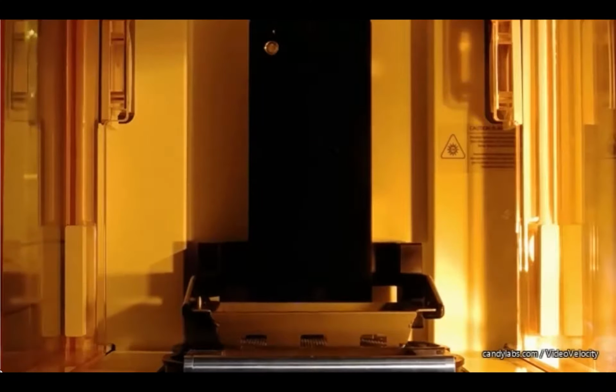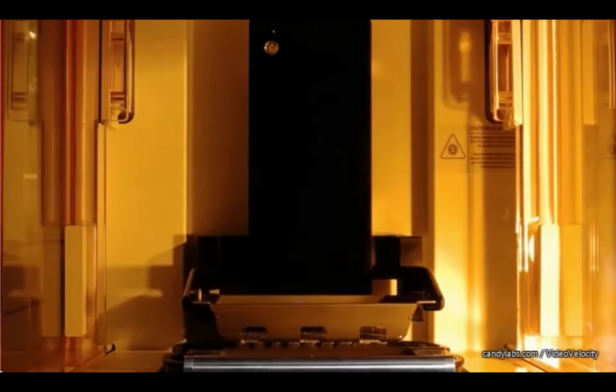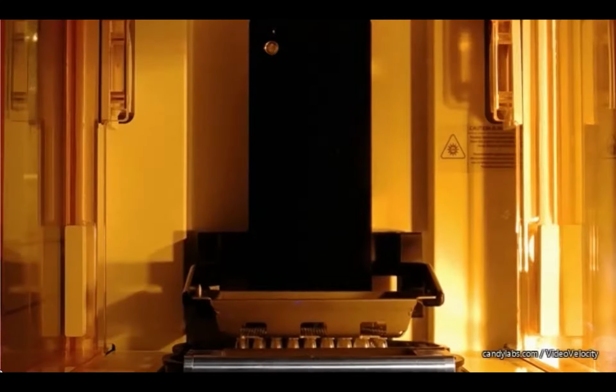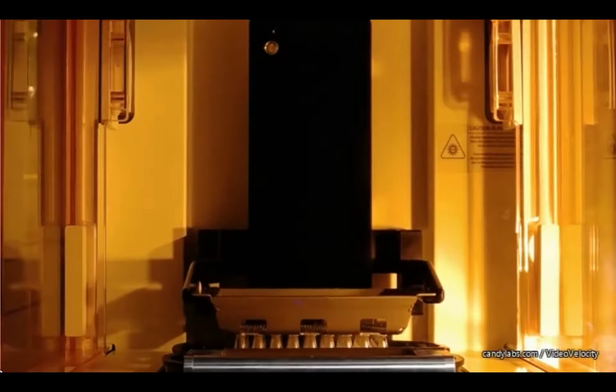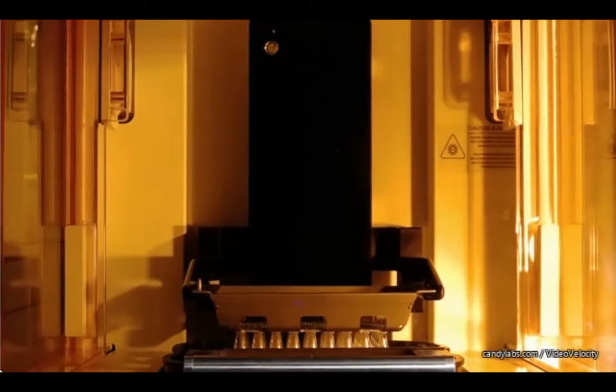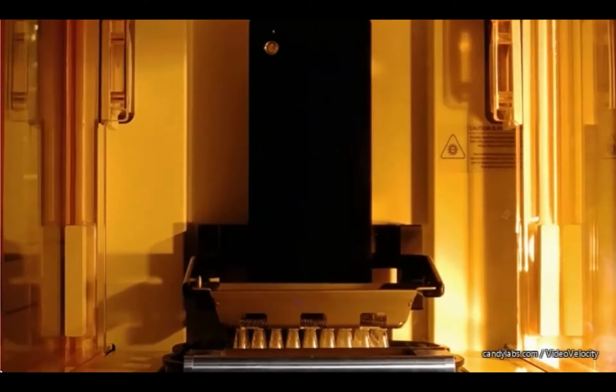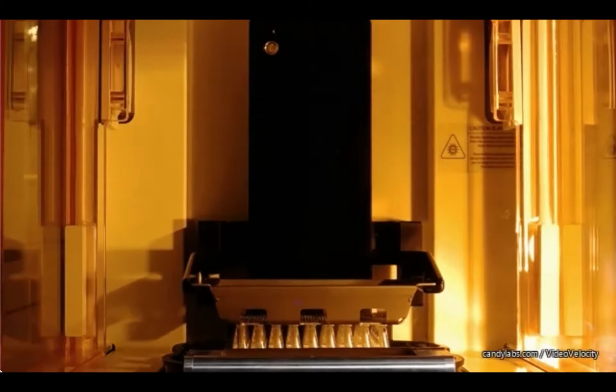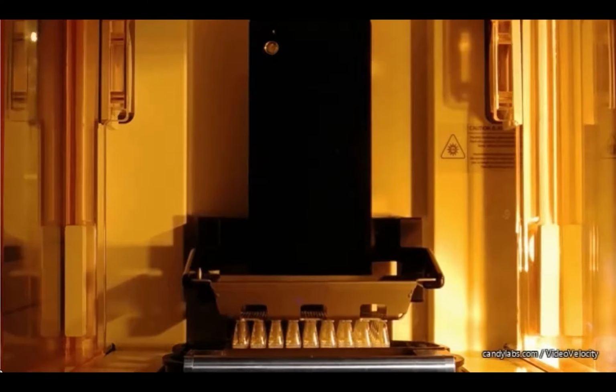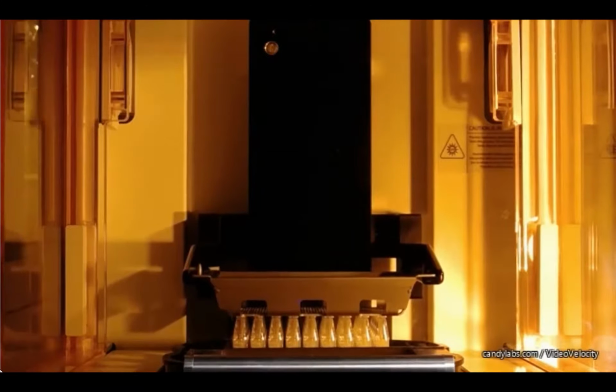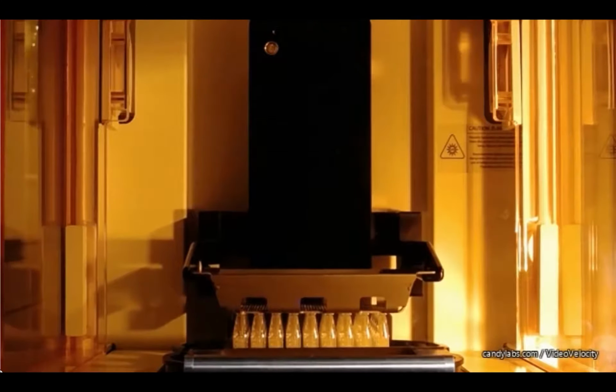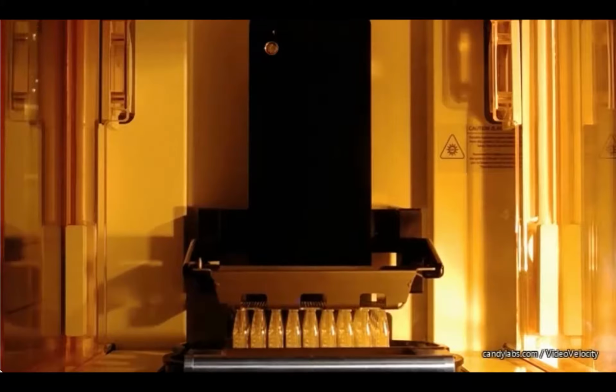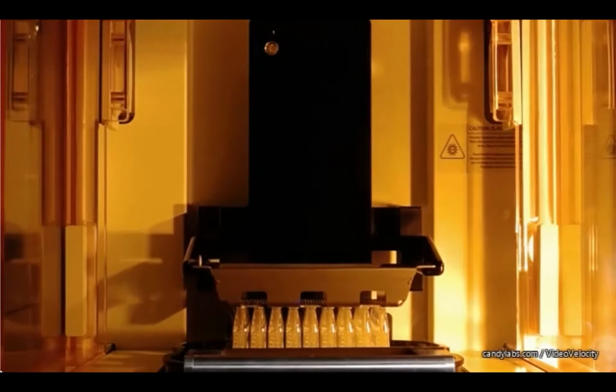Where the UV is projecting onto the tray is a semi-permeable plastic, which allows for oxygen to flow through the plastic, meaning that there is no stress on the part. So it's always free to move up and down, which is really nice because it enables us to print a vertical part with very little stress, very little support structure. It's a very quick process. Again, we're printing at 50 microns. This is a 4-hour print condensed down into a 2-minute video.